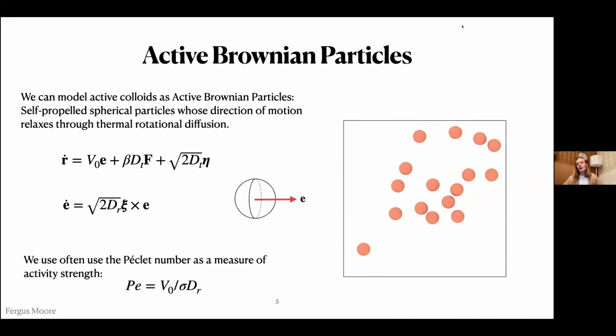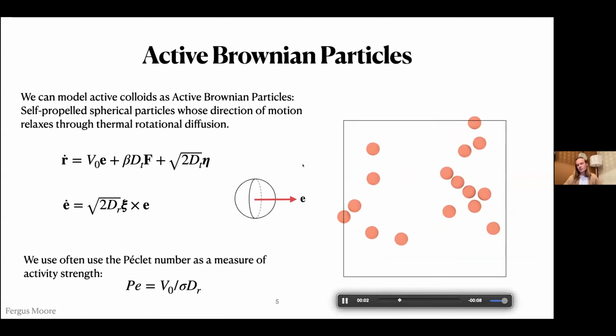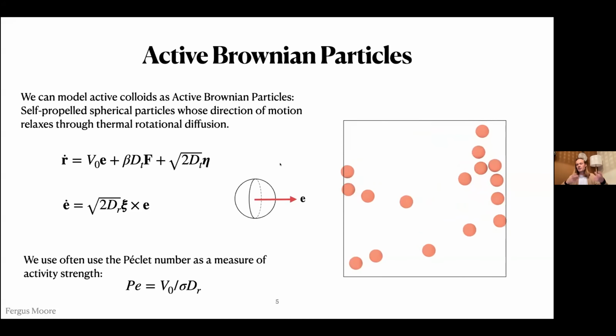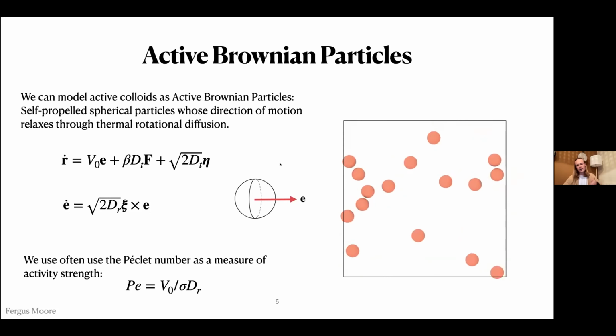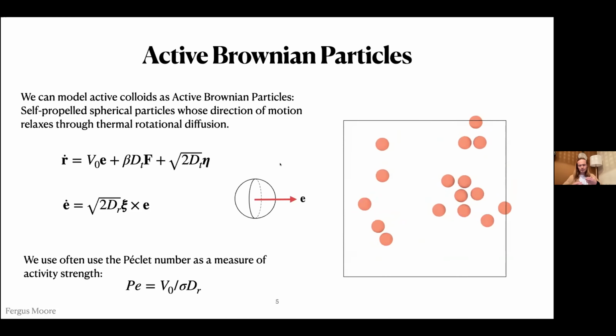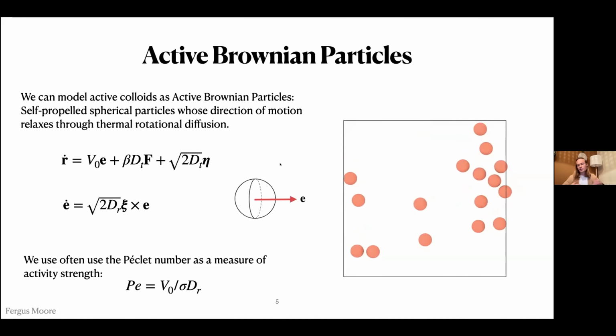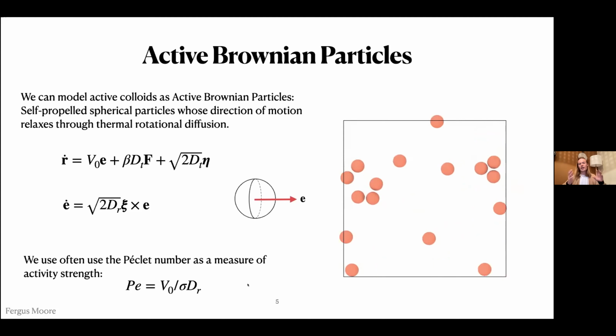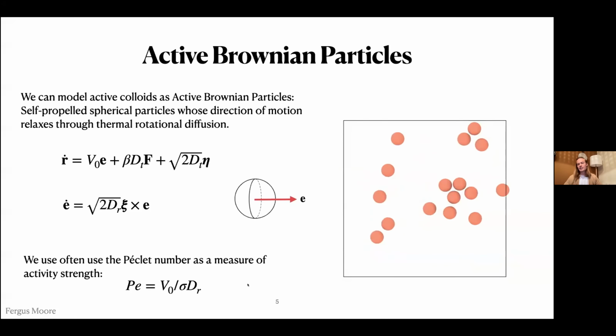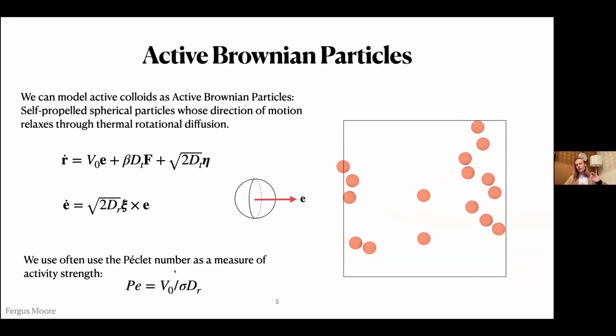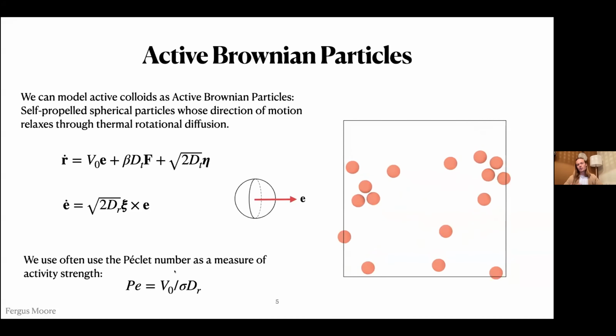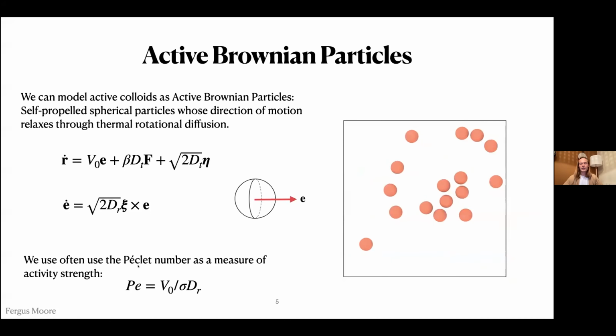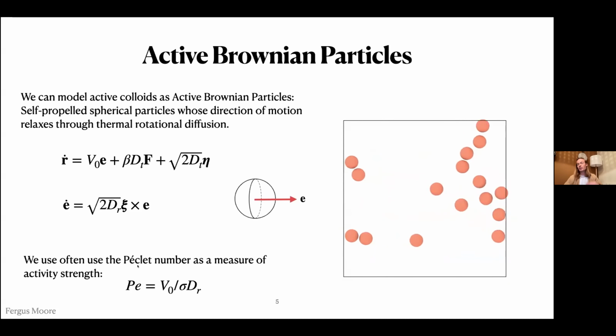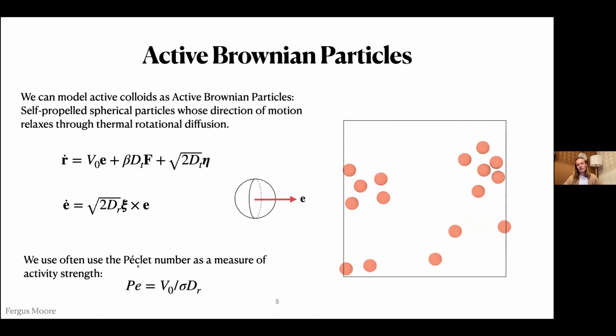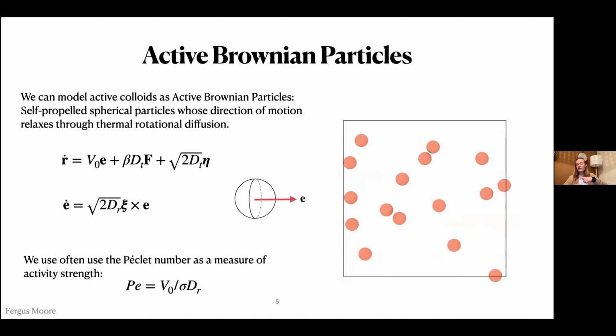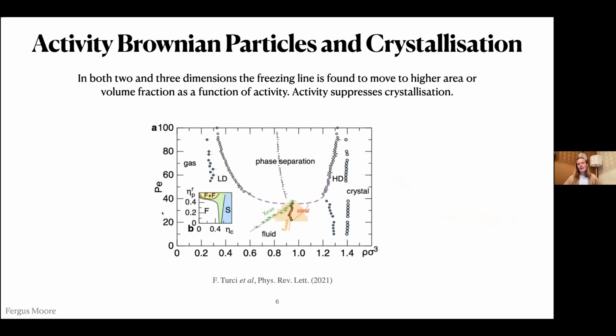That creates dynamics such as this, which is a little 2D simulation I've made. You can see that they're feeling Brownian effects, but if you watch one for a little while, it'll go in a particular direction, and then this direction will diffuse and change, and they interact with each other. I also want to introduce the Peclet number, a useful metric for describing these systems, which is a ratio of the strength of the propulsion to the thermal noise. We can increase the constant velocity, or we can reduce the rotational diffusion coefficient so the direction persists longer, as ways to control these systems.